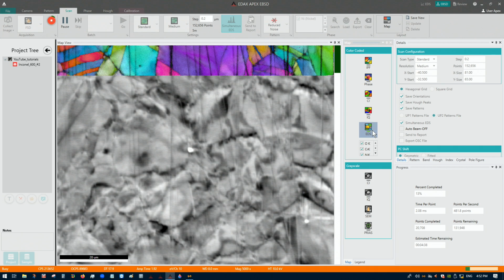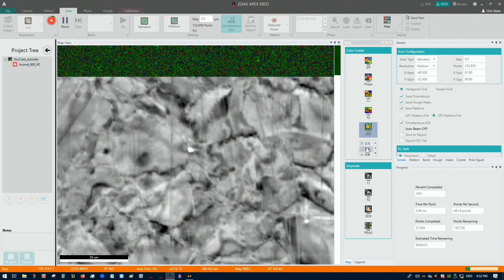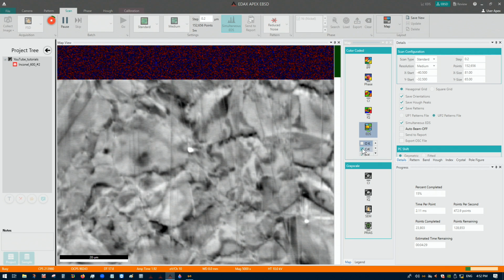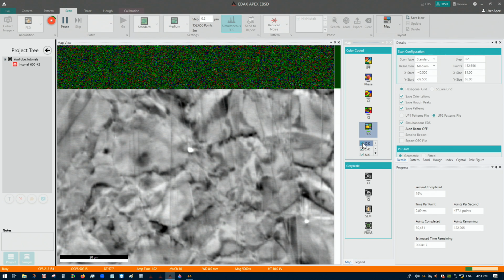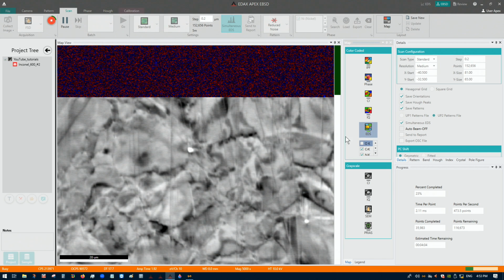And we can look at the EDS here. So these are all the different elements. You can turn certain elements off. Okay, so nickel is red, chromium is blue. You can change the colors of these after the fact, but we'll leave this on for now. Okay, now it's doing a histogram stretch with these, so there really probably isn't this much oxygen, especially since we deoxidized the surface. So take that with a grain of salt. So let me turn off oxygen though.